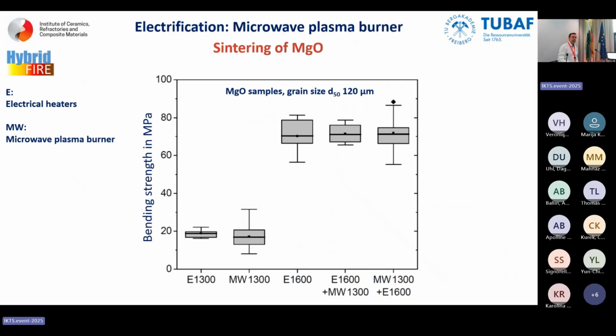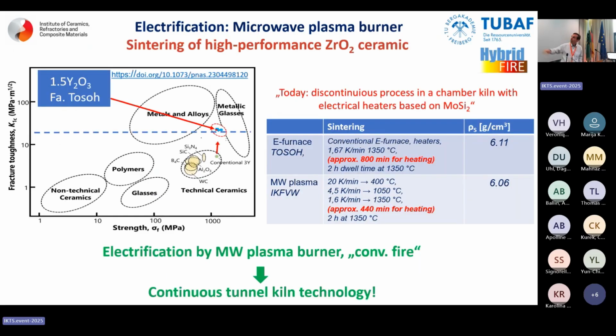We have done this. Marie Oppelt and Christine Dietzer have dealt a little bit with magnesia. We are in the same area of strengths. I don't want to go further. We have fired Tosoh 1.5Y2O3, yttria stabilized tetragonal zirconia, no? So a high-tech ceramic. And we have seen we can heat faster. And not only this, keep in mind, I have a burner which is circulating the temperature. The other was conventional heating elements.